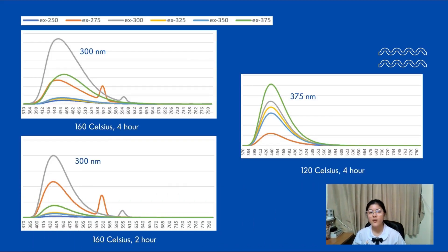For 160 degrees Celsius conditions, when the exciting wavelength is 300 nanometers, they show the most intensity emission.